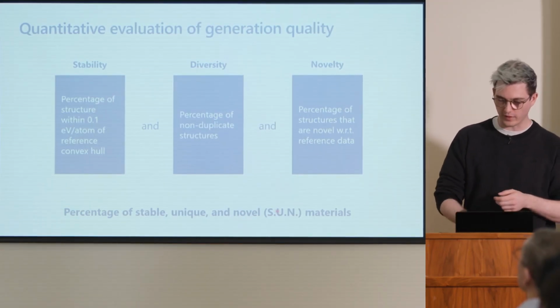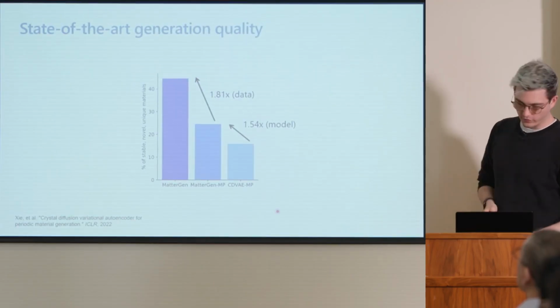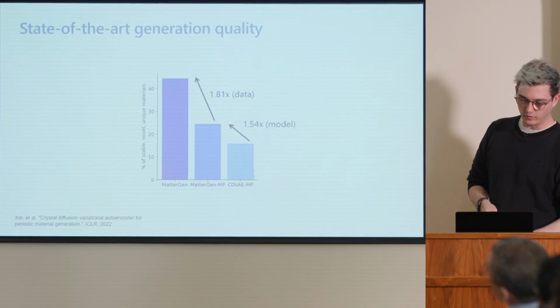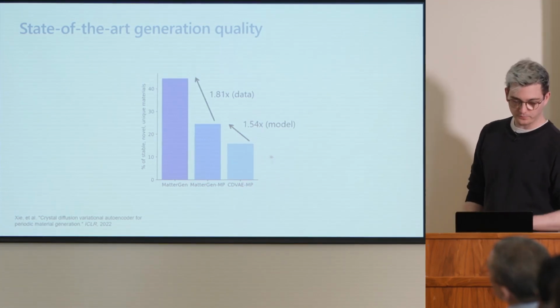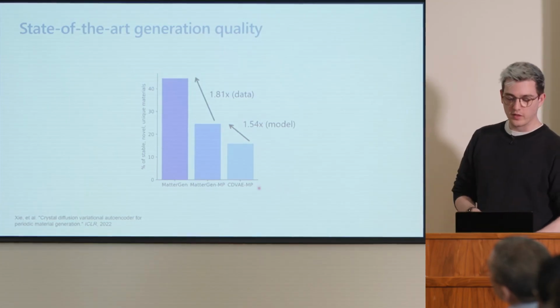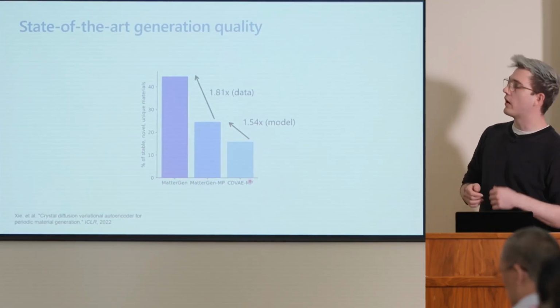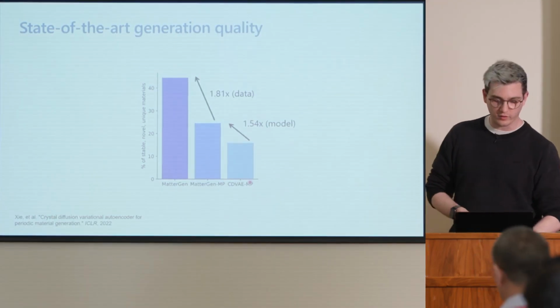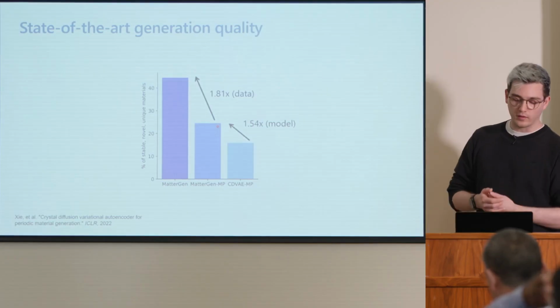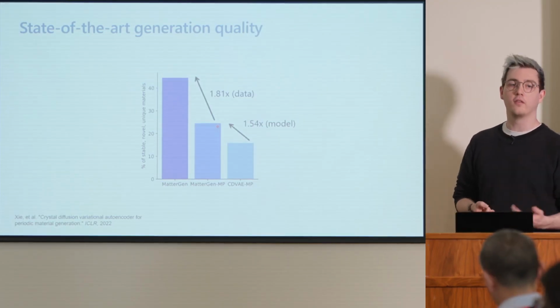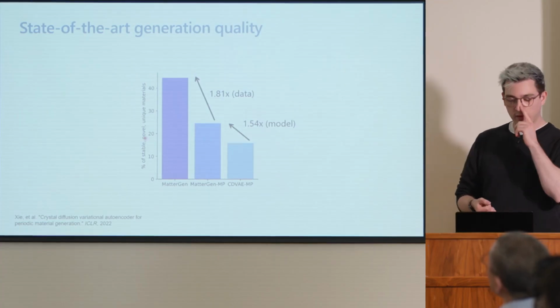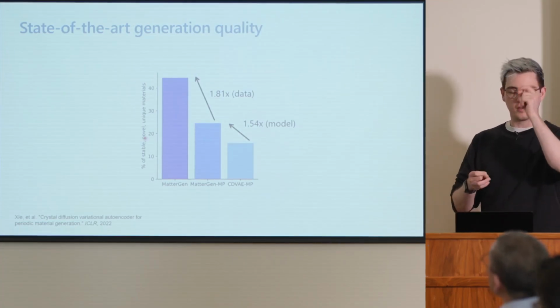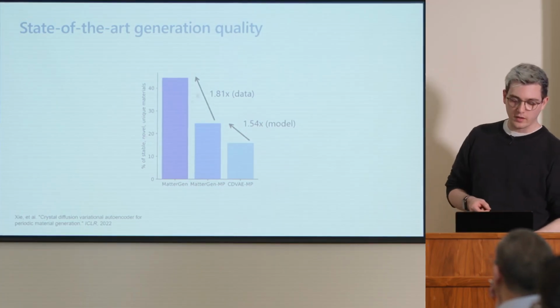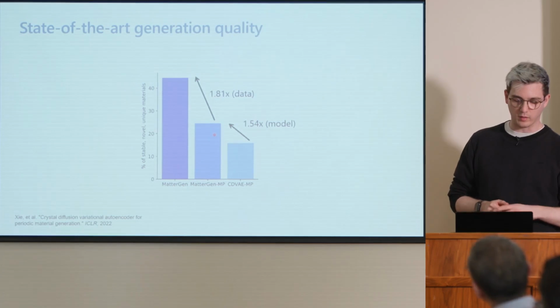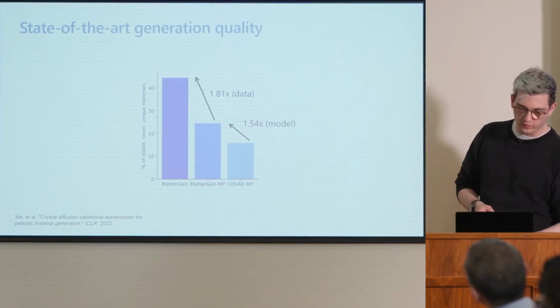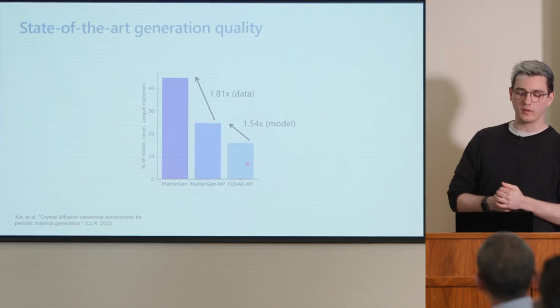All right, so with that out of the way, we start from the current state of the art, or the previous state of the art, which is CDVAE, Crystal Diffusion Variational Autoencoder, that was trained on MP20, and then we swap in our custom diffusion process and our own model architecture. We see a 1.5 times increase in the percentage of stable, novel, and unique materials. And then the second step is we take our big data set and train a model on that, and that leads to a 1.8 times increase in the number of stable, novel, unique materials. So this leads to an almost 3x improvement over the previous state of the art.